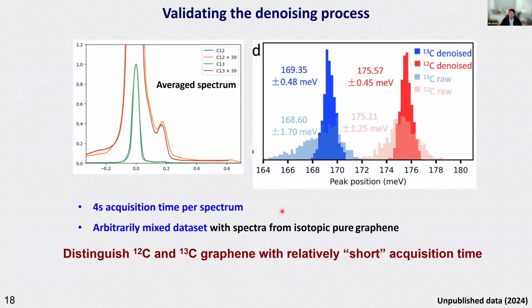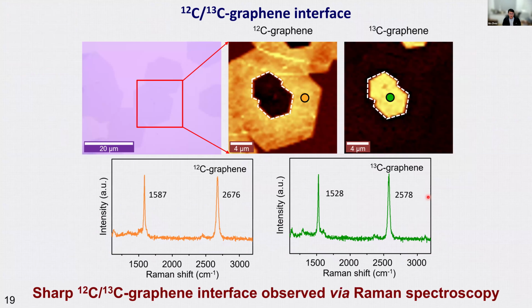And here's just a test that after applying the denoising process, we can go from a broad distribution where we mix the carbon-12 and carbon-13 spectra to a very high accuracy analysis. So with this process, we can look at isotope mixed samples.